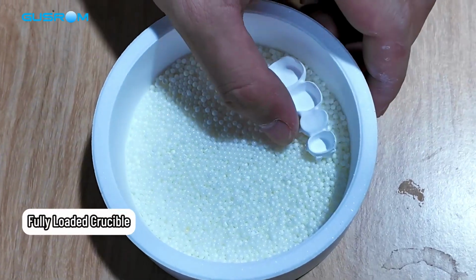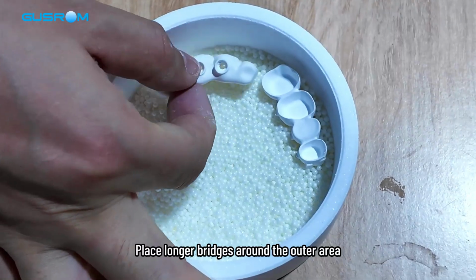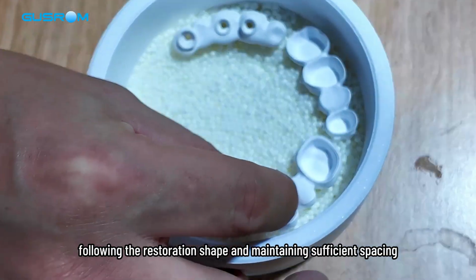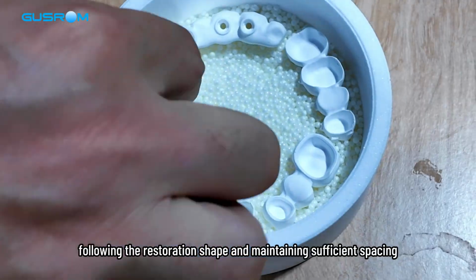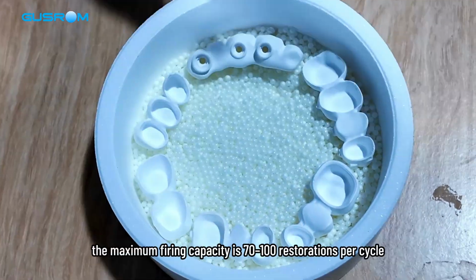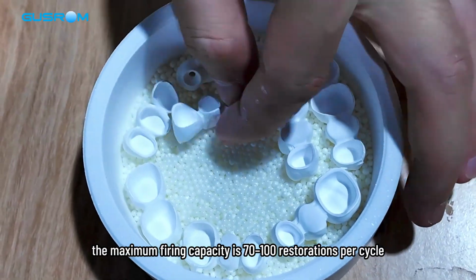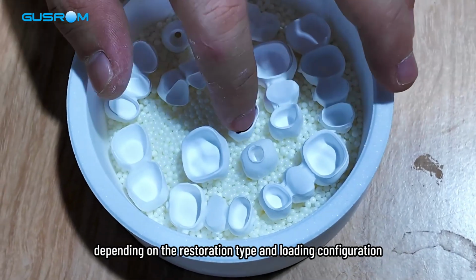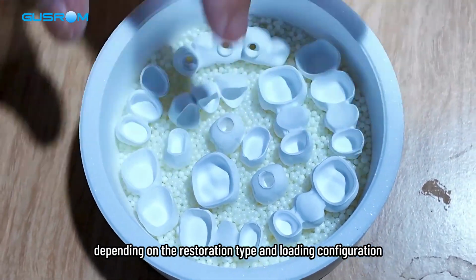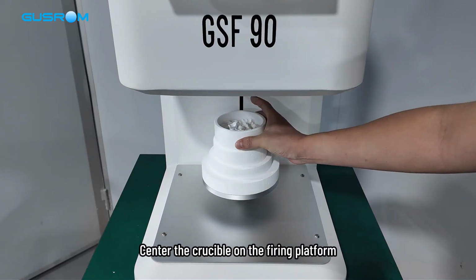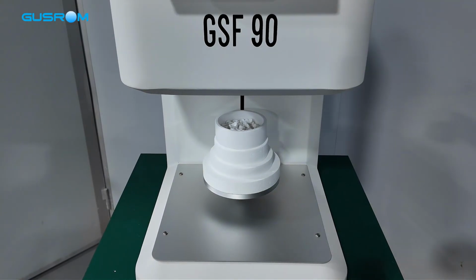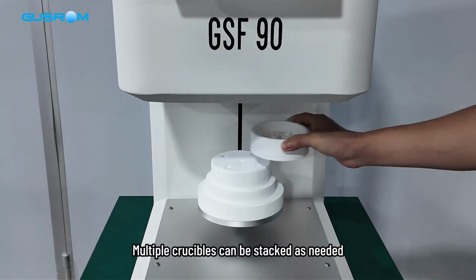Fully loaded crucible. Place longer bridges around the outer area, following the restoration shape and maintaining sufficient spacing. With multiple crucibles stacked, the maximum firing capacity is 70-100 restorations per cycle, depending on the restoration type and loading configuration. Center the crucible on the firing platform. Multiple crucibles can be stacked as needed.